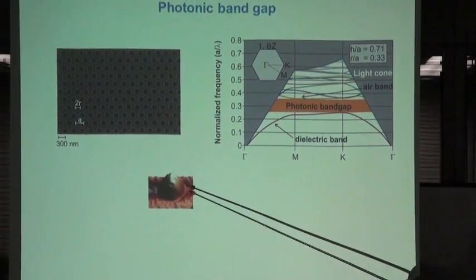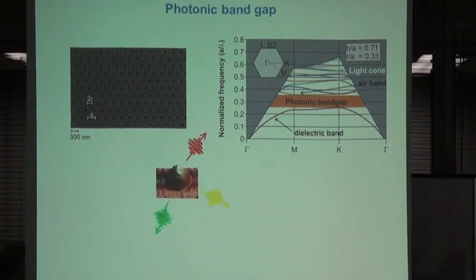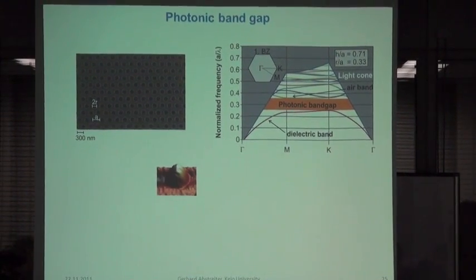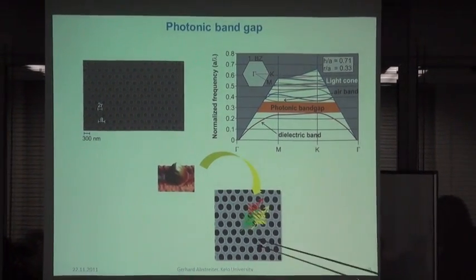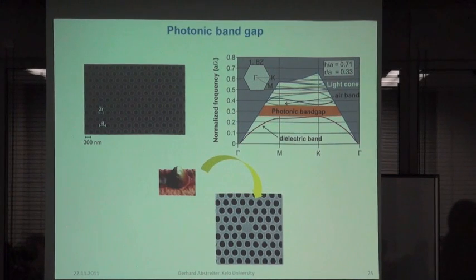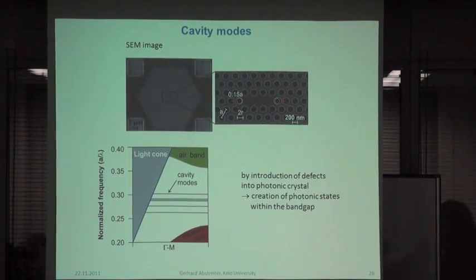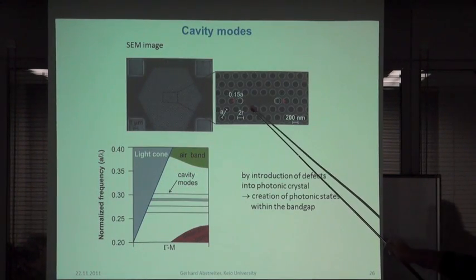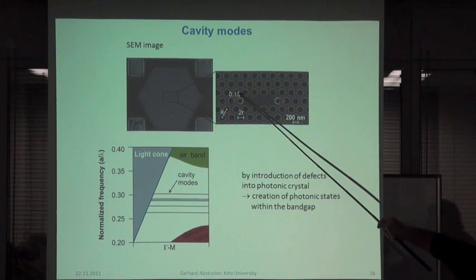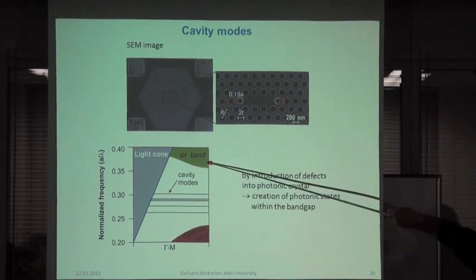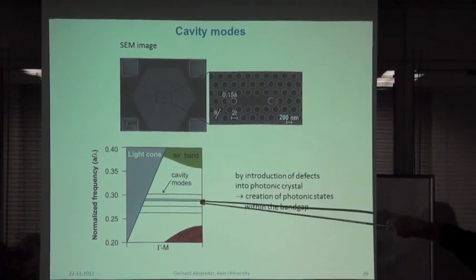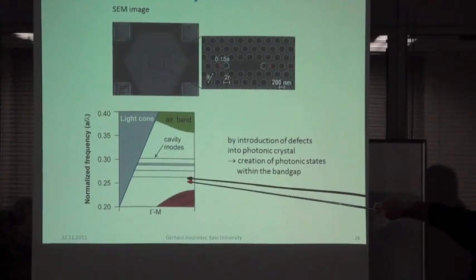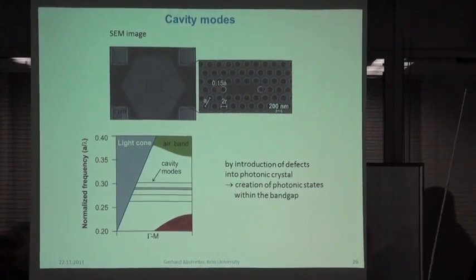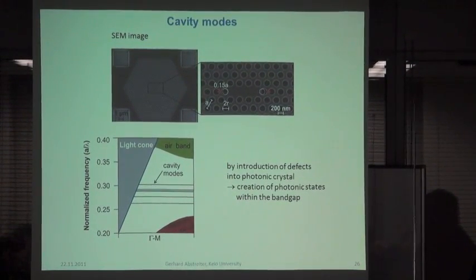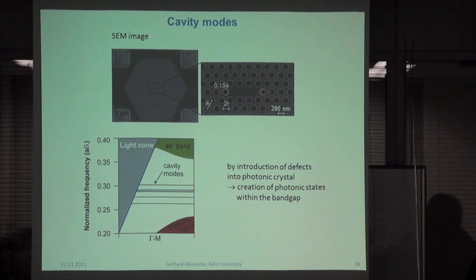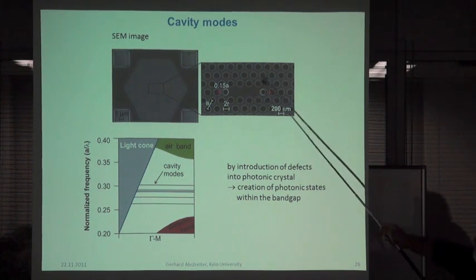So what happens if I have a quantum dot which normally emits light in all directions? In such a photonic crystal, I can redirect the light in one direction. Actually, when I have these defects, and depending on the defect, we have in this photonic band gap also cavity modes. This is like a defect in a semiconductor. If you have a donor in a semiconductor, it gives you a level in the band gap, and this is the same in the photonic crystal.